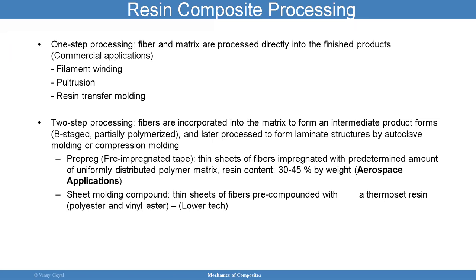A two-step processing is a situation where the fibers are incorporated into the matrix. And when you do that, you're forming an intermediate product form. We call that B staging, and I'll discuss that later. And later it is processed to form laminates, right? So we discussed how a laminate is comprised of lamina. And the lamina in this case is the intermediate product form. I put all the lamina together, I stack it up at different ply angles, and then I'm able to process it further through an autoclave, which then allows me to get the finalized product.